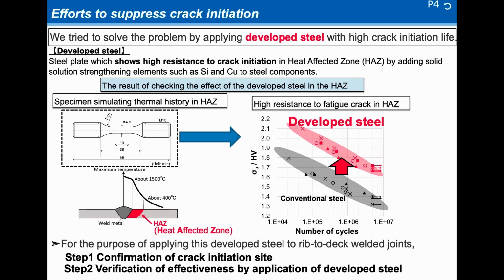The fatigue tests were conducted on specimens cut into small pieces from the developed steel by giving them a thermal history simulating welding. The chart on the right shows an S-N diagram. The developed steel has higher fatigue properties than those of conventional steel. So, for the purpose of applying this developed steel to rib-to-deck welded joints, we confirmed the crack initiation site and verified the effectiveness by application of the developed steel.